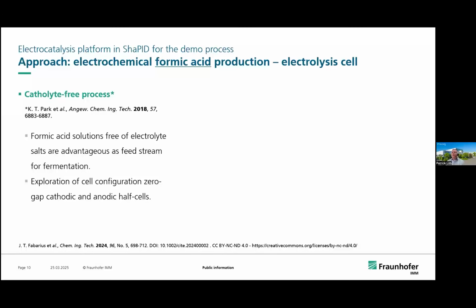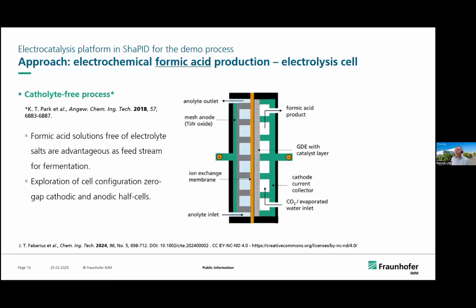The advantage is that we have a formic acid solution free of electrolyte salts, which is advantageous as a feed stream for fermentation. The cell configuration looks like this: we have zero gap cathodic and anodic half cells. The decisive point is that instead of a liquid electrolyte, where we have to dissolve the CO2, we use CO2 with evaporated water. So the water is coating our gas diffusion electrode, and we have small amounts of water in the system. In contrast to a liquid electrolyte, we improve the mass transfer properties. This is the decisive point in the cell configuration.